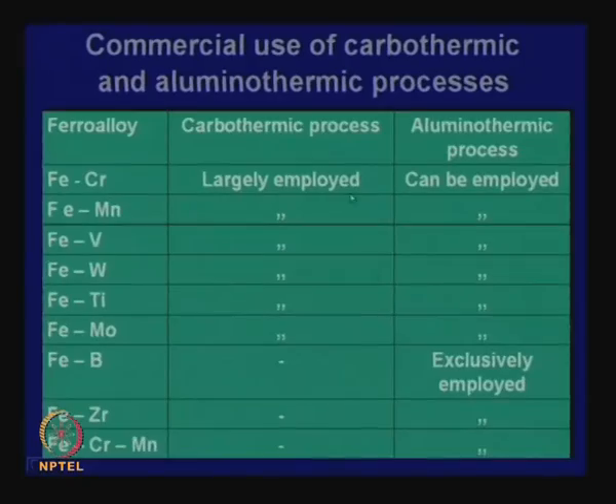Now, here I have indicated that this carbothermic process is largely employed for ferrochrome production, ferromanganese production, ferrovanadium, ferrotungsten, ferrotitanium, ferromolybdenum. This will not work for the boron, zirconium or FeCrMn, whereas the aluminothermic process, means reduction by aluminum, can be employed in all the cases. It can be universally applied. There is one example, ferroboron, exclusively employed only by aluminothermic reduction, whereas in the other cases, there are many places where it is carbon reduction with subsequent refining, or aluminothermic or calciothermic reduction. Both processes are employed.